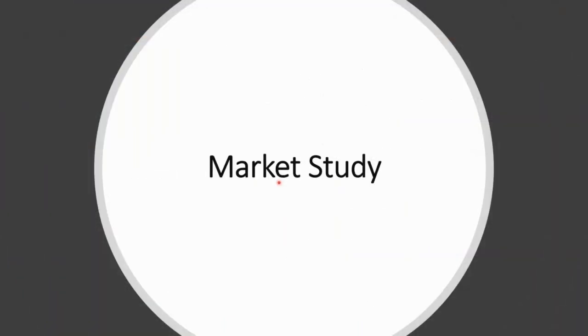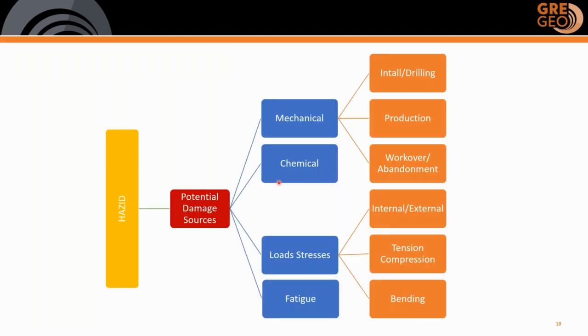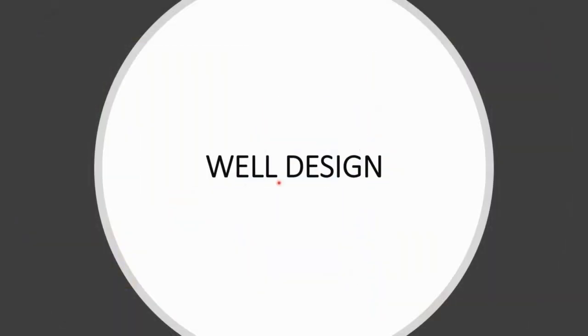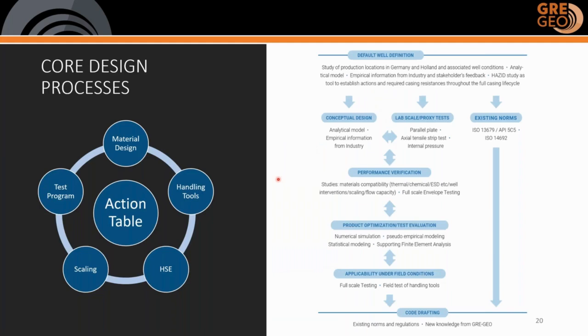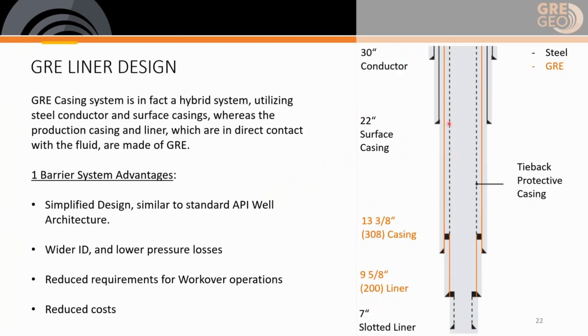We have not tested it per se throughout our project, but this kind of technology has already been used in France, in the Paris Basin. There are transitional pieces especially made for the transition between GRE and steel, and hangers. The hangers for the liners are used in a similar way to those for nickel-based and chromium alloy steel casings. So there are specialized GRE-to-steel transition pieces that take care of the contact between these two materials. This is already developed technology, applied and tested in the field.